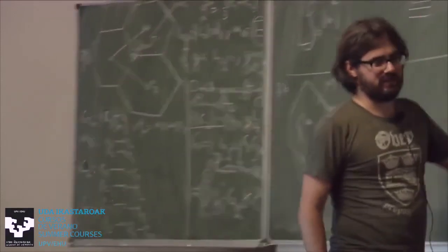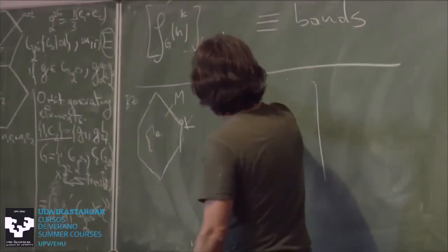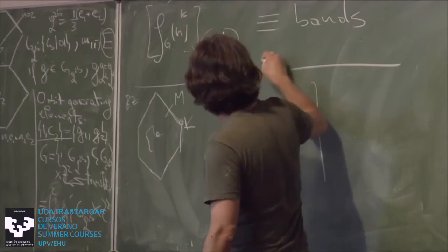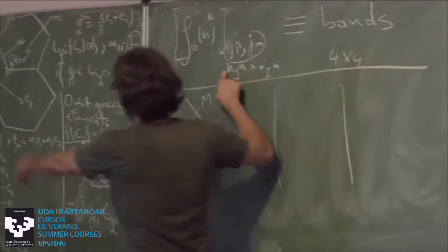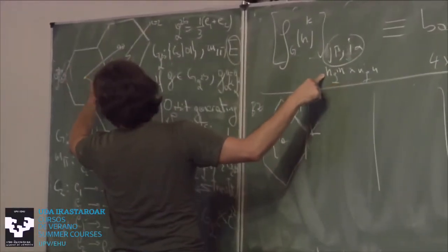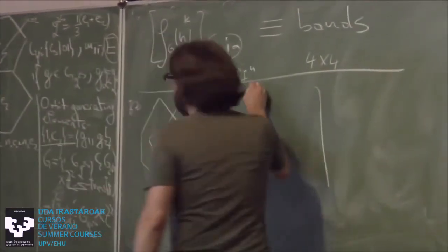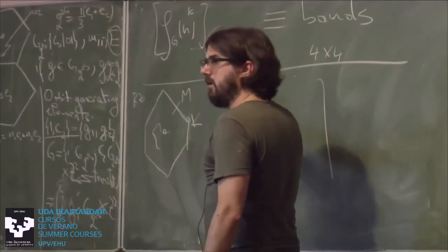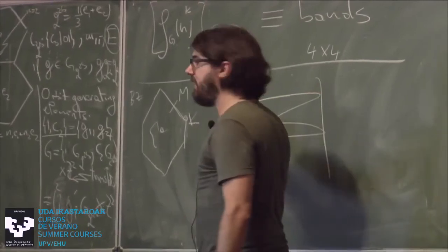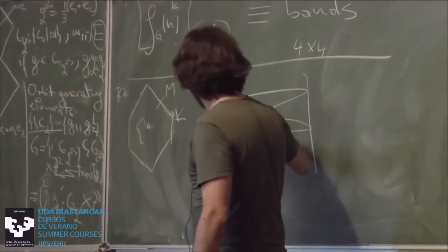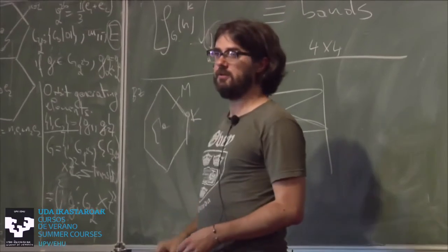And then we're going to ask, what does this band representation really mean? The moral of the story is that at each k, this particular band representation is a 4x4 matrix because I have 2 Wyckoff positions and the representation of the high symmetry stabilizer group was 2-dimensional. So this means that graphene at every k has 4 bands, and that these bands, if they come from localized orbitals, which is the way I built this representation, are connected in the Brillouin zone.